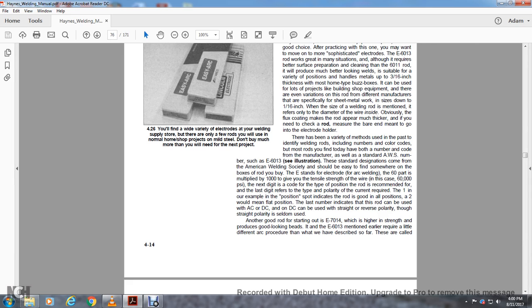The first digits, 60, multiplied by 1,000 give you the tensile strength of the wire, 60,000 psi. The next digit of the code is the position the rod is recommended for. The last digit refers to the type of polarity for the current required. 1, for example, indicates the rod is good in all positions. 2 would mean flat position. The last number indicates the rod can be used with AC or DC. DC can be used with straight or reverse polarity, though straight polarity is seldom used.